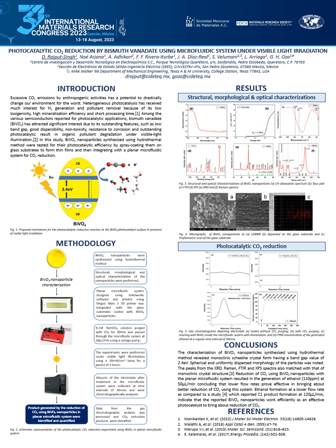To finally confirm the crystalline structure and the form of bismuth vanadate, XRD studies were performed, and when the XRD diffractogram was compared with the JCPDS card number for the monoclinic scheelite form of bismuth vanadate nanoparticles, we found an exact match, and hence we finally could conclude that indeed the nanoparticles synthesized using the hydrothermal method were of the monoclinic scheelite form of bismuth vanadate nanoparticles.